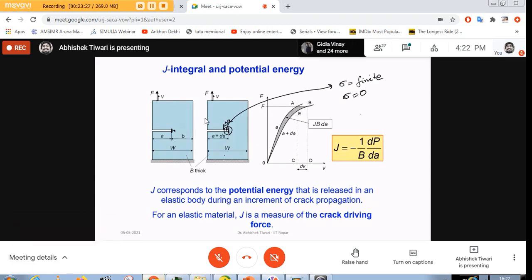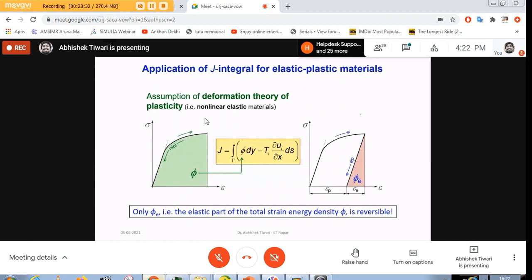And that is where there is a problem. Now let us look at this, which is what I explained. That was the experimental part, and if we have to calculate this J integral numerically, then we can simply apply this equation in finite element analysis software, and we can calculate these terms, where phi is strain energy density, and T is traction, and all those other terms I have already defined. So all those data you can straight away get from finite element software, and you can calculate this J integral.